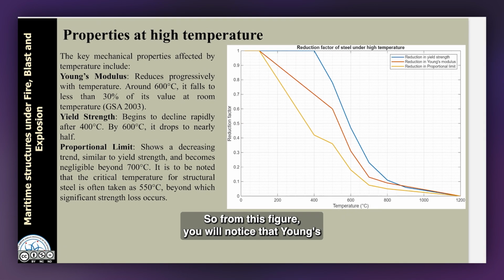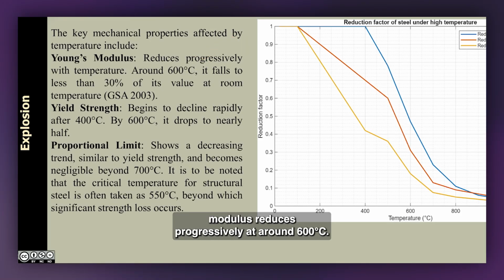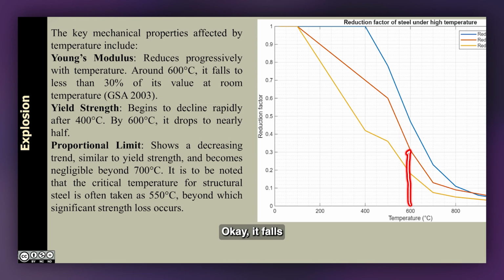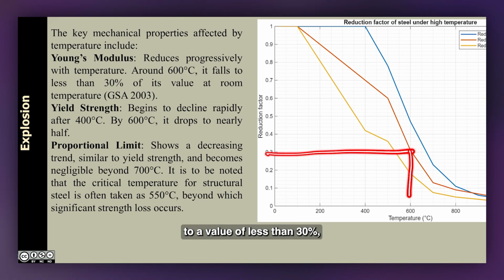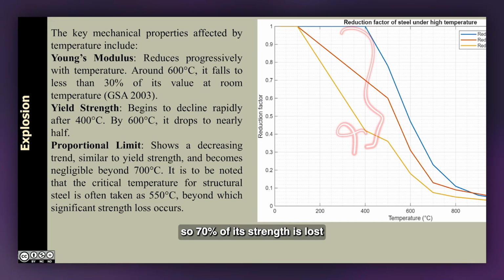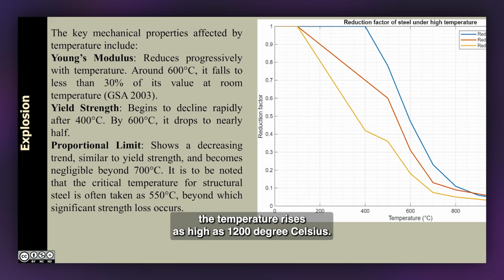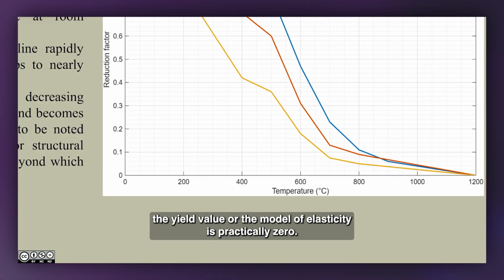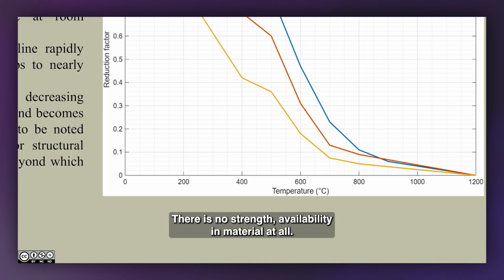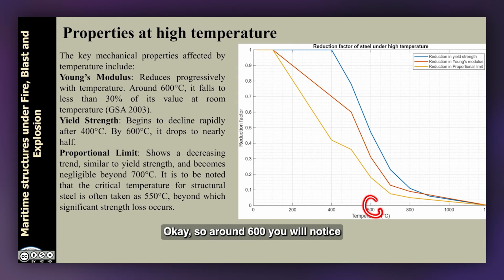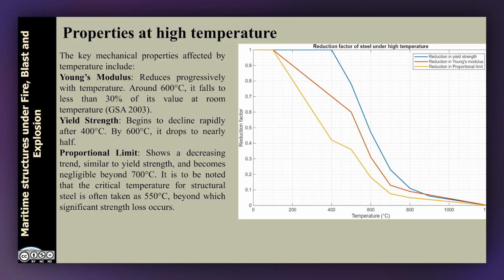whereas the y axis plots the reduction factor. So, from this figure you will notice that Young's modulus reduces progressively, and at around 600 degrees Celsius it falls to a value of less than 30%. So, 70% of its strength is lost at 600, whereas in maritime construction, especially under hydrocarbon fire, the temperature reaches as high as 1200 degrees Celsius. So, practically, friends, at 1200 degrees Celsius, the modulus of elasticity is practically 0. It means the steel has started flowing. There is no strength available in the material at all. Okay. So, around 600 you will notice that the reduction factor is 0.3. So, 70% of the strength is lost. Okay, that is very important.